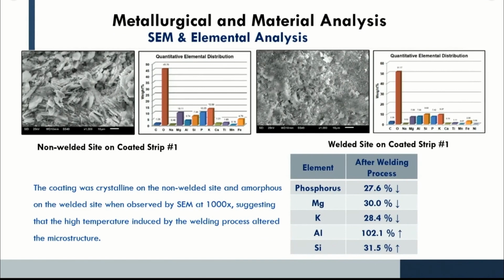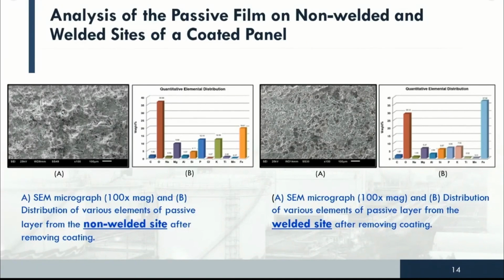We took chips from the non-welded sample and from the welded sample, and then we looked at the SEM analysis with EDX. And what we found, the same thing. Where there is no welding, we have crystalline. When there is welding, we have more amorphous, as indicated by phosphorus, magnesium, potassium decreasing in the welded one, whereby aluminum, silicate increase in the welded one. We removed the coating and looked at the first layer formed. What we found, the same thing: amorphous versus crystalline.